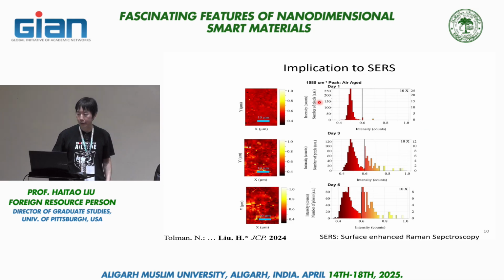I want to briefly show that we can detect SERS signal, and in this case, what you're looking at is a heat map, essentially the intensity of Raman signal, because this is a SERS substrate. We're just going to call it SERS signal. From top to bottom, we look at the same area as a function of exposure time to air. On the top is 1 day after the sample was prepared, we left it in air, and then 3 days and 5 days. And what you see in the heat map is the appearance of those yellow dots. Now, yellow means higher Raman intensity.